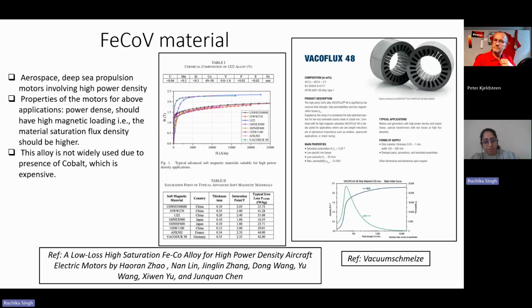The other day, I was reading a paper with a graph where you see the comparison between different grades from different countries and thicknesses and typical losses, and you can see the saturation levels as well. Definitely, it saturates at a very high B. The material they were using was 1J22 alloy, which is a Chinese grade, an iron-cobalt-vanadium grade. You see the saturation level is around 2, so it saturates quite higher as compared to the other grades.